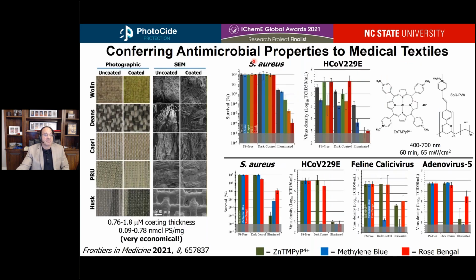As a further example of our technology, we've been able to confer antimicrobial properties to medical textiles using, again, this bicomponent mixture of a photodynamic agent with a UV photocross-linkable polymer. You can see that on the left-hand side, we have a variety of different medical textiles provided to us by Vestcom America. And you can see in the photographic images prior to our coating process and then after coating with our photodynamic materials, we're able to see in the SEM images the effect of the coating on the fiber morphologies as well. Using these images with a whole other host of characterization methods, we've been able to determine that our coating thicknesses are roughly 1 micron.